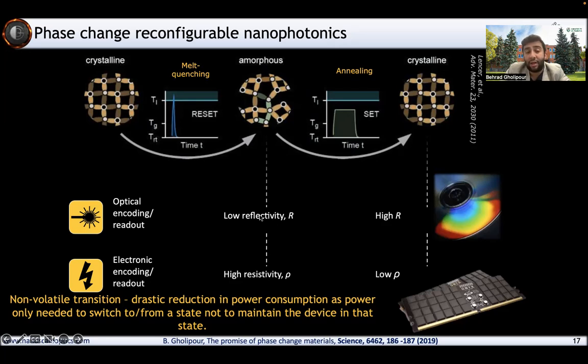The amorphous phase has a low reflectivity, is very transmissive, but it has a high resistivity because of all those electron scattering at the boundaries that you would anticipate. In the crystalline case, we have high reflectivity. It's a much more crystalline material, and it has a low resistivity because of the nice lattice ordering. And switching between these can be induced by singular pulses or trains of pulses, depending on the protocol you're using.